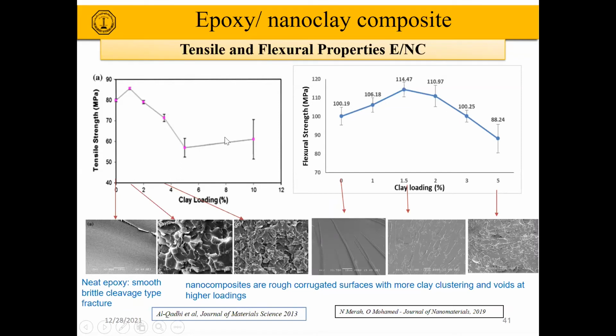That is because of the presence of clustering of nanoclays and the presence of voids. Actually, we were not able to obtain exfoliated structure after 2% of the nanoclay loading. But up to 1.5, the tensile strength was improved, and the flexural strength also was improved up to 1.5. You can see this is about 14% improvement in the flexural strength.